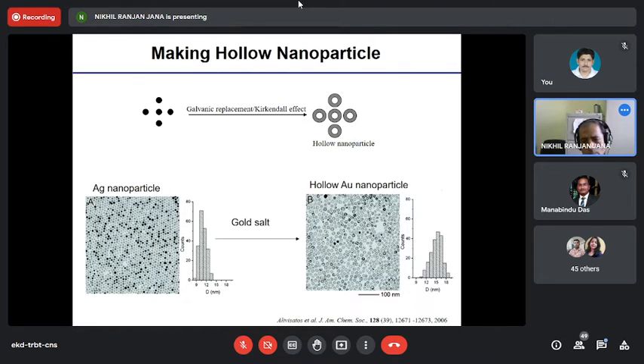And why does it make hollow? Because in nano size, the reaction is very vigorous, and silver moves its place. Silver moves from inside to outside in order to react with gold ions that are present outside. So that's how the hollow shape is formed. That's called the Kirkendall effect. Vigorous reaction leads to place exchange. Silver changes its place from inside to outside. And outside, because it becomes silver ion, it leaches out into the solvent. And instead of silver, gold is deposited at the outside. That's how hollow structures form.